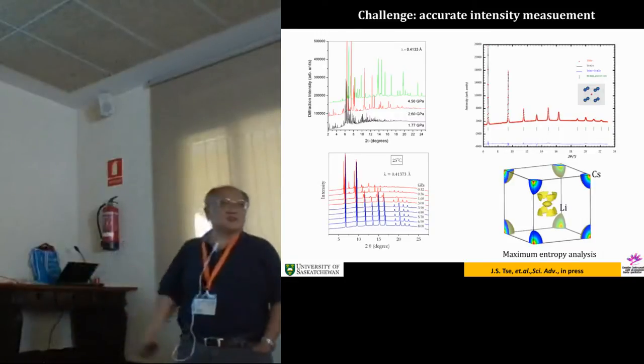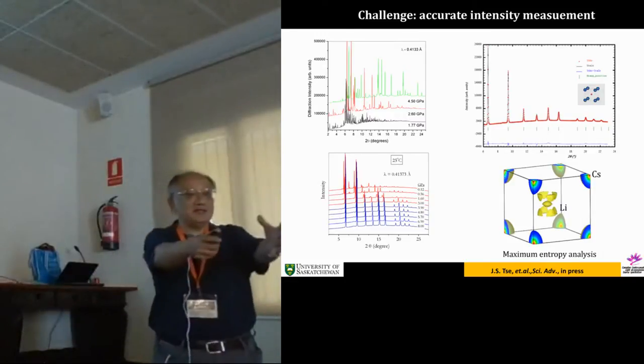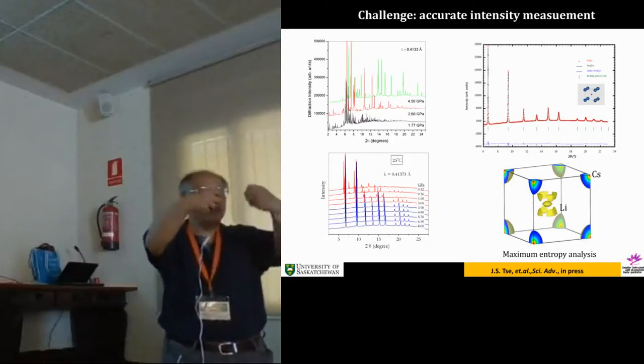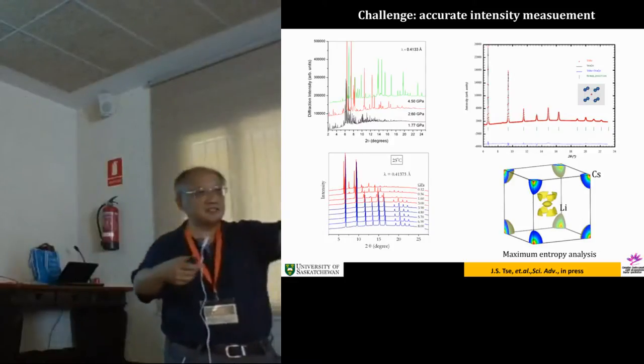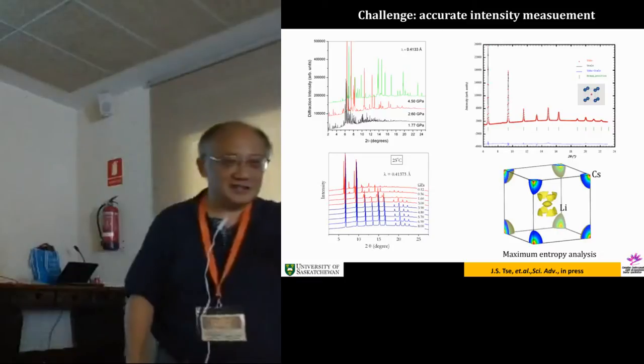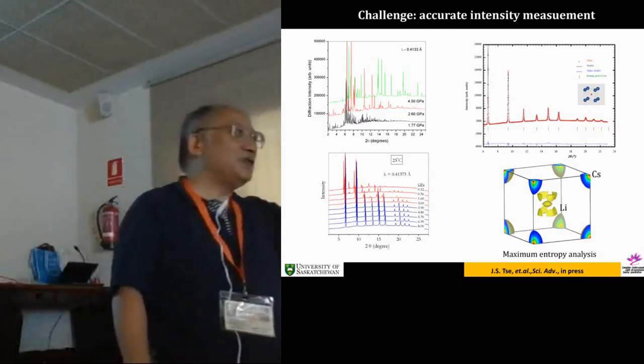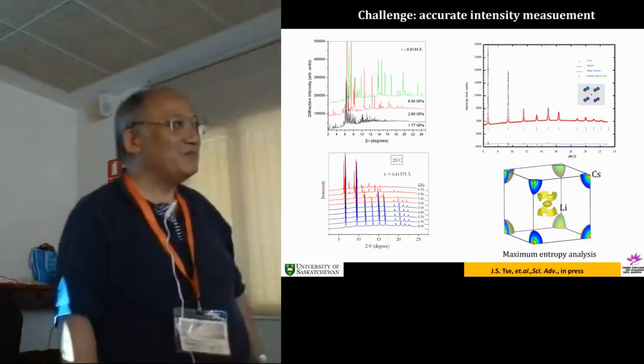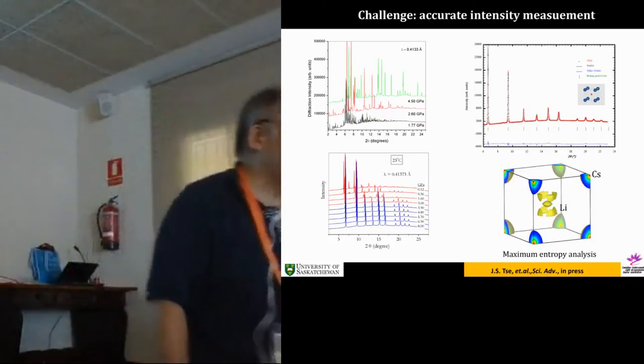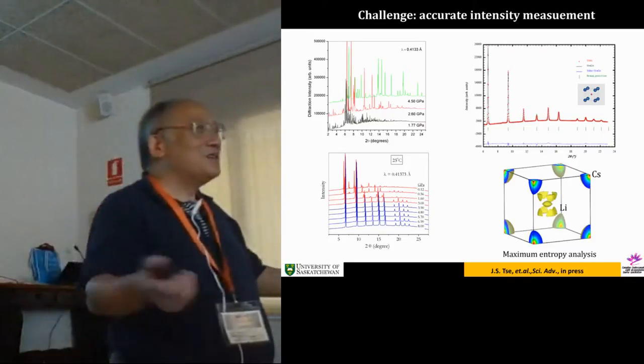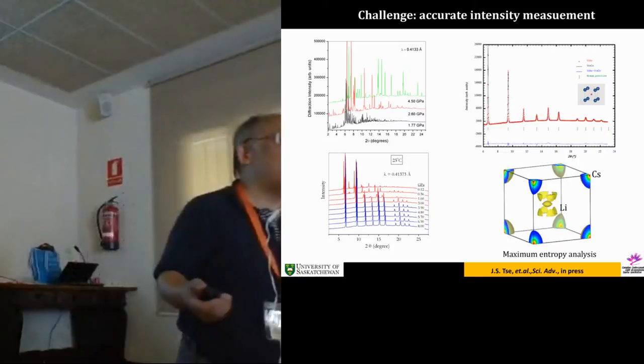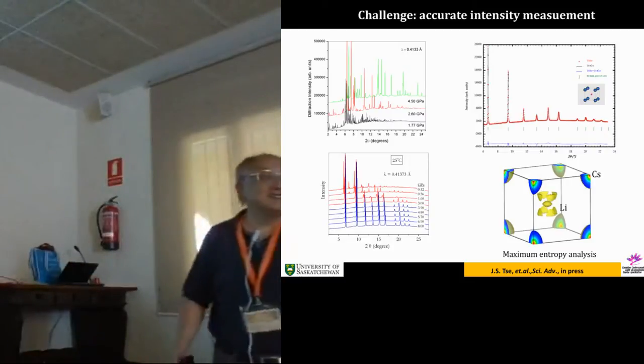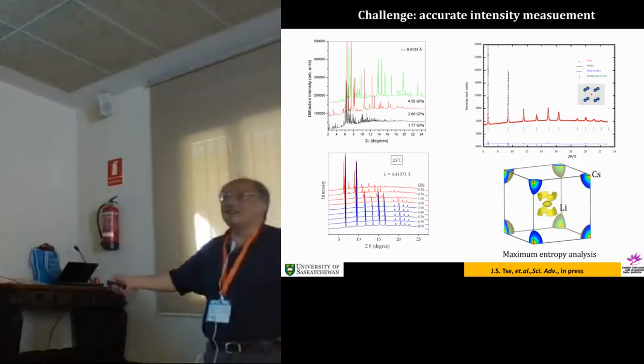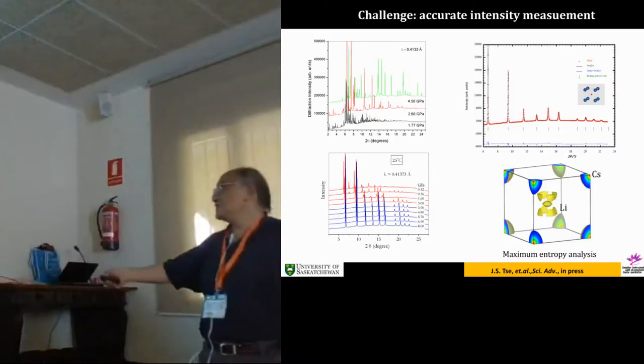So what's the structure? What's the cubic? I have cesium and lithium. Are they a substitution alloy? That means the positions are 50% cesium, 50% lithium, or are they some other alloy? I don't know. So the easiest way is to take the intensity, do a maximum entropy analysis, and you can count the electron density here. It is cesium, and this is lithium.